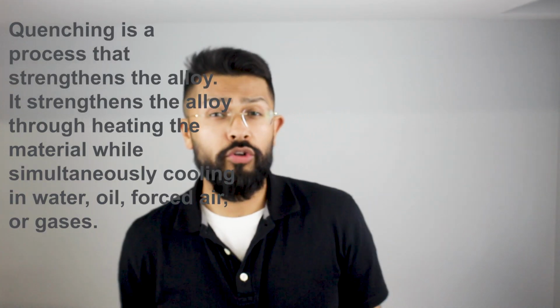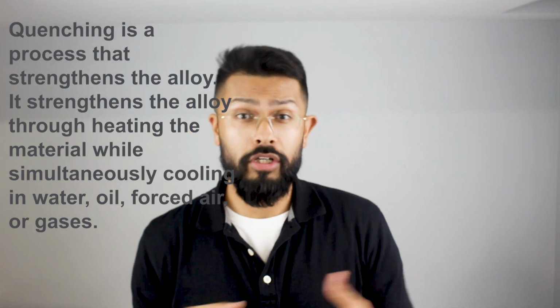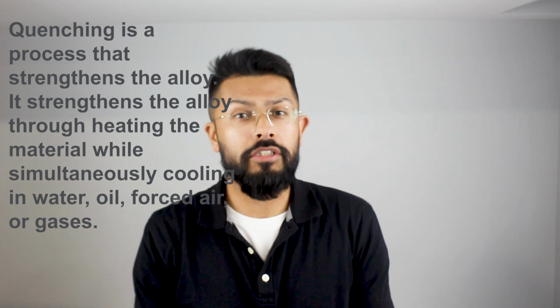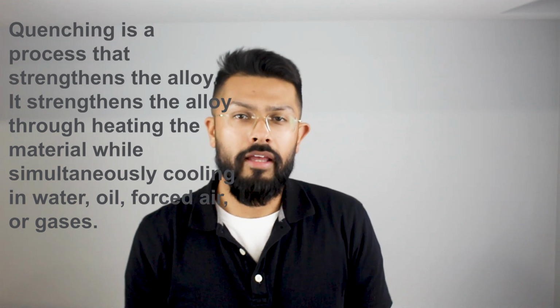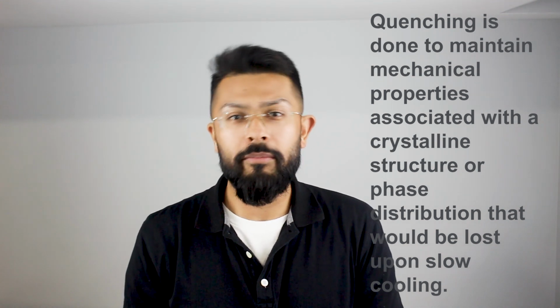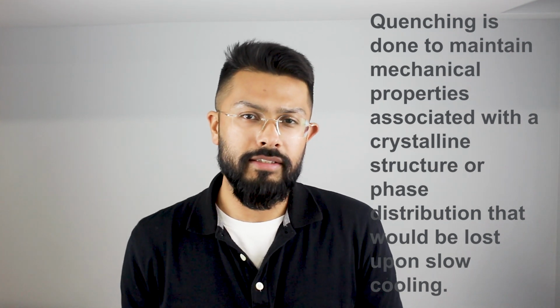On melting the alloy prior to casting, any metallographic structure which is possessed as an ingot is lost and a new crystal structure is created as the metal freezes inside the mold. It is important to quench the gold alloy castings before they cool to the range of temperatures within which heat hardening takes place. An alloy which is allowed to cool slowly to room temperature will undergo both precipitation and order hardening prematurely. Before any alteration in shape of such a casting is attempted, it must be softened by cooling rapidly